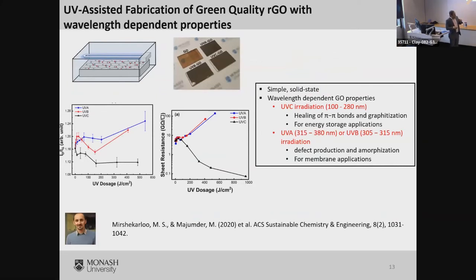We started to play around with UV-assisted fabrication of graphene oxide. And this is not something unknown. However, one of the things we were able to discover was that not all UV light is the same. There are certain wavelengths, UVA and UVB, which make more amorphous carbon and make defects, whereas UVC, which is here, actually reduces defects, heals pi bonds, and increases the electrical conductivity. All right, we have shown that with electrical measurements as well as Raman spectroscopy data. So one of our learnings was that the UV radiation could be very specific and tailored for the purpose of modifying materials.